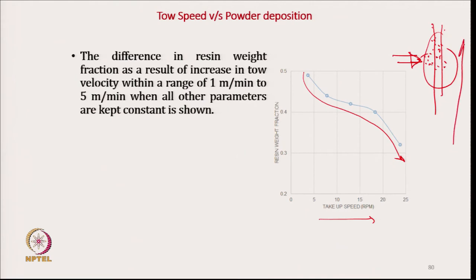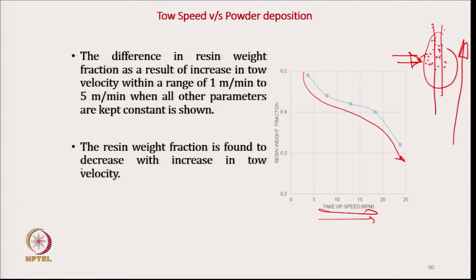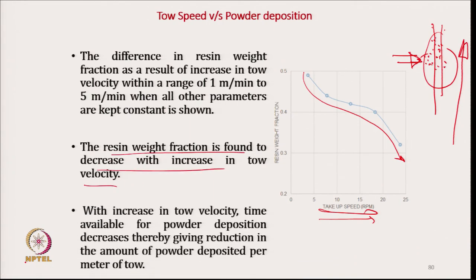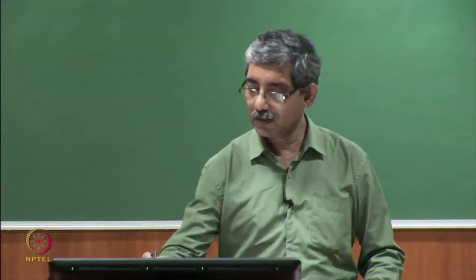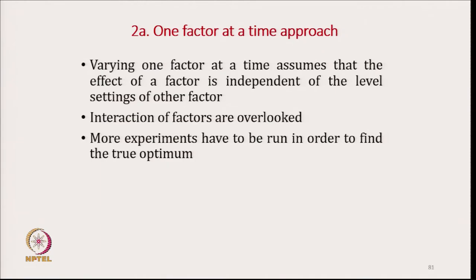If we increase the speed, residence time is less, so less powder will get deposited. The resin weight fraction is found to decrease with the increase in velocity, because the time available for powder deposition decreases. In the one-factor-at-a-time approach, we changed one parameter and kept the other parameters constant. In this approach we have done other experiments also.